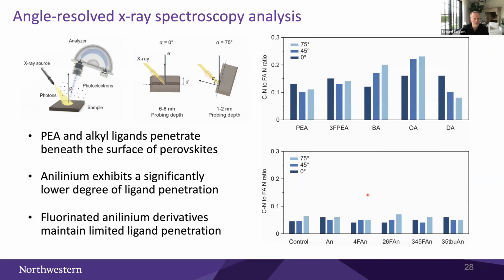as-created devices. So Soman, in this recent report, studied, initially using angle-resolved X-ray spectroscopy, the penetration of various candidate ligands beneath the surface of the perovskite. Some, PEA as our canonical example, will invade and will form the 2D layer on top, some 10 or 20 or 50 nanometers in. And others, and Soman particularly found the anilinium and fluorinated aniliniums, were able to limit the ligand penetration and substantially form a surface layer only.